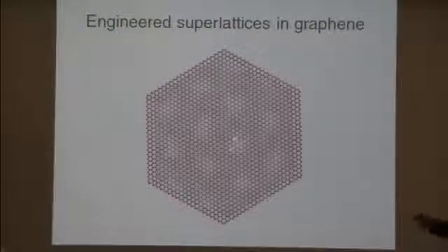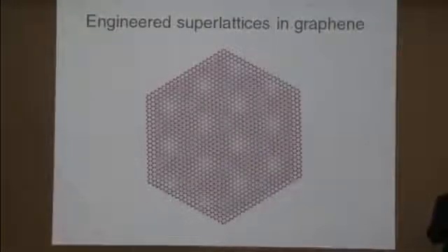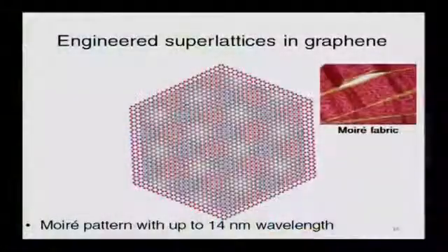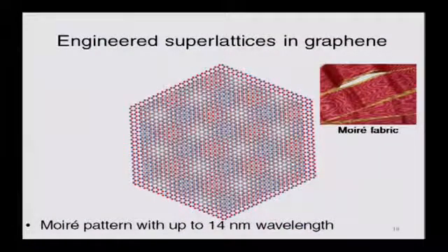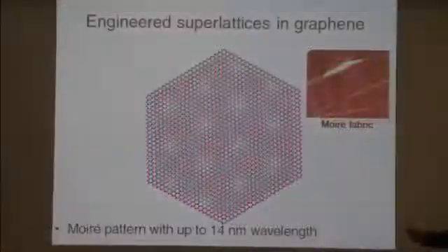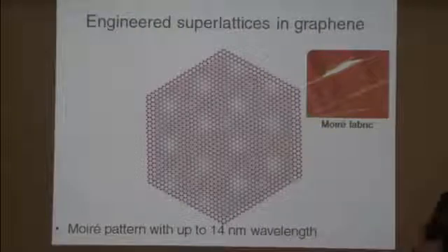And especially at perfect rotational alignment. If we put the crystals lined up one right on top of the other so that they're not mismatched, all we're sensitive to is the mismatch in their lattice constants, which is just small enough that we can make the perfect size superlattice to observe the Hofstadter butterfly. So it turns out this is exactly the same effect. If you have Moiré fabric, that's what it is. You have two lattices. They're not quite aligned. And so you end up with some superstructure which has a much longer wavelength than, say, the spacing between the fibers in Moiré silk, right?